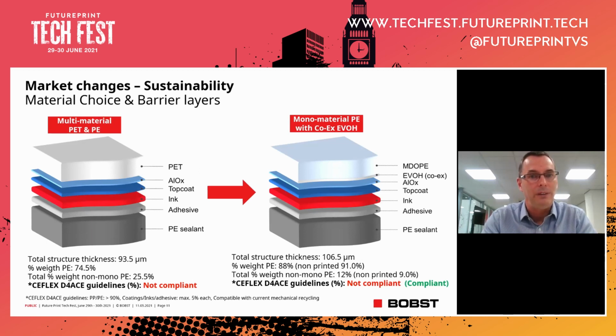It consists of a standard 12-micron polyester film with a thin AlOx barrier layer, and that also has a protective polymer layer on top of the AlOx, which is then reverse printed before being laminated to a 75-micron polyethylene sealant web. And to help illustrate the potential recyclability via the amount of mono material in the structure, again, we've used the CEFLEX guidelines as a basis to quantitatively compare solutions.